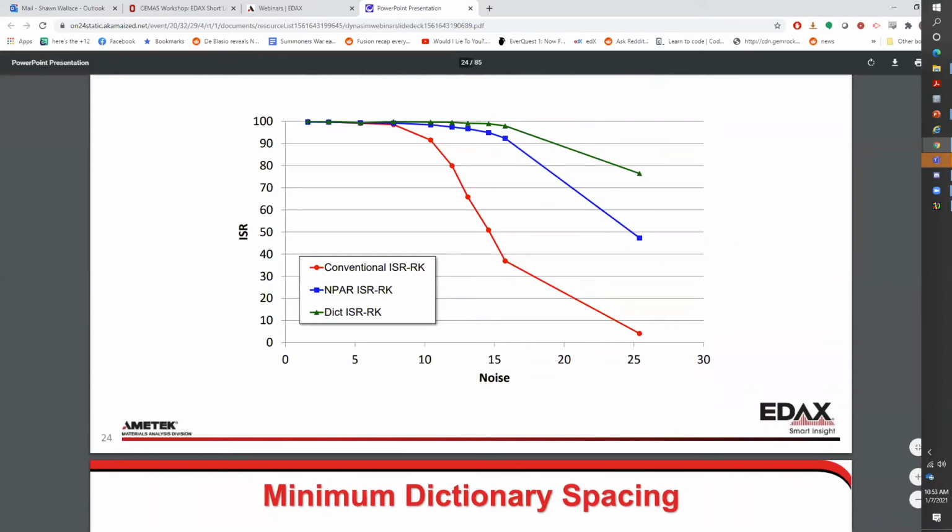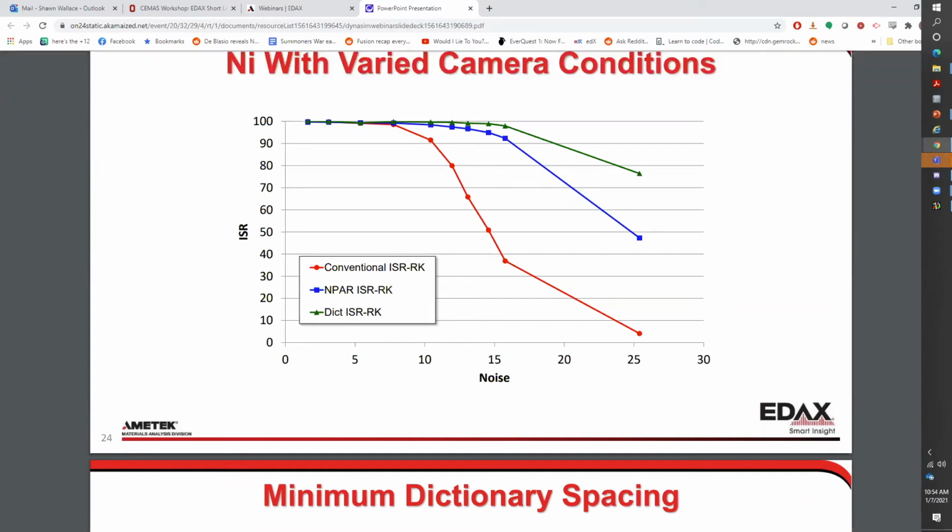Can we do cleanup after dictionary or before? You can do it, probably usually you do something like that after doing the dictionary. Why? The dictionary indexing is indexing, right? So you can have your initial indexed data set and you can do that. But there's also a way to do what we would call CI selective dictionary indexing, where I can use things like that CI value as a basic filter to make it easier and quicker to run the dictionary process.